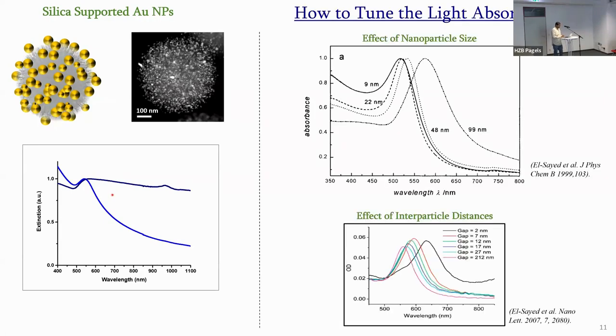Now, when we looked into the literature, we found that if you change the particle size, obviously the lambda max is changing, which is shifting from one lambda to another. It's not going to let you harvest the entire broadband of the light. And then there is another nice concept by El-Sayed, where they said that if you bring the nanoparticles closer, then the electron clouds of these nanoparticles start interacting with each other. That is the plasmonic coupling. And if many nanoparticles come together, lots of these electron clouds interact, and that allows you to broaden the light absorption behavior. Still not completely broad, but this at least gives an indication that plasmonic coupling could be the way to produce a material which can provide broadband light absorption.